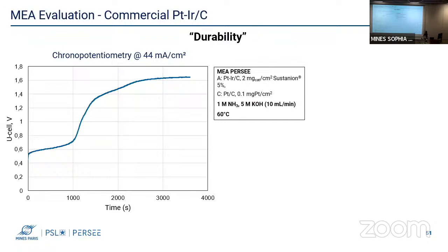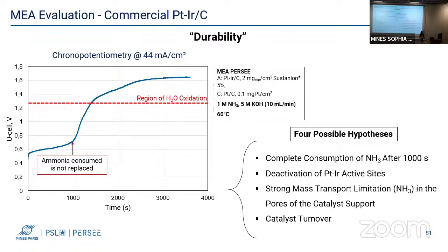In order to test the durability of the catalysts, we conducted chronopotentiometry at 44 milliampere per centimeter square. We observe a slight increase in the voltage at the beginning of the reaction, which could be attributed to the non-replacement of ammonia molecules as they are being consumed. A sharp increase in the voltage is then observed, which stabilizes at 1.6 volt, which is already the region of water oxidation. In order to try to understand this phenomenon, we propose several hypotheses.